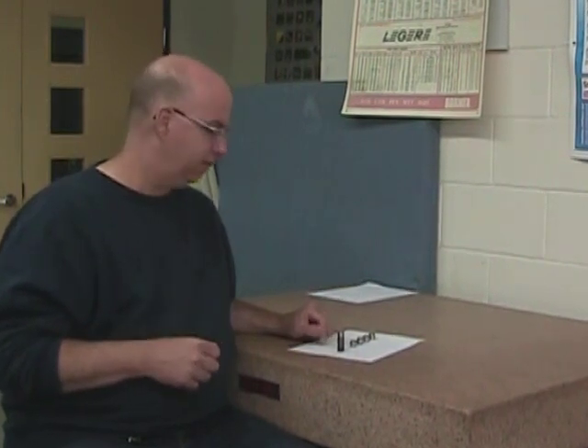So in conclusion, we can say that for the tool steel bar that we had up here, a dark orange color was really the best color for quenching and hardening this tool steel. We saw that a light orange or even a very light orange created a piece that was just as hard but very brittle. And the dark red color just wasn't hot enough to really get this quenched and hardened. So, dark orange. You'll notice that from one steel to the next, depending on the alloy you're using, these temperatures can fluctuate somewhat, but not very much, surprisingly little actually. So, shoot for that dark orange and you'll do okay.